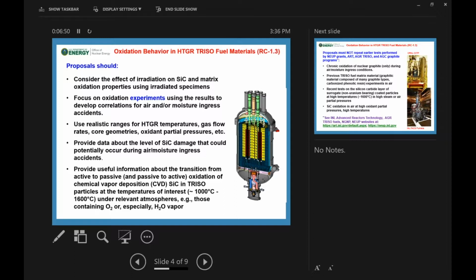air or moisture ingress. And this is important because we will be doing integral tests with our advanced gas reactor experiments that we have. We have furnace tests, and we will have a large furnace that's being developed now, and your information will be helpful in developing that furnace too. We want you to provide useful information for that transition to active to passive and back again, passive to active oxidation for the CVD that's inside that TRISO particle.